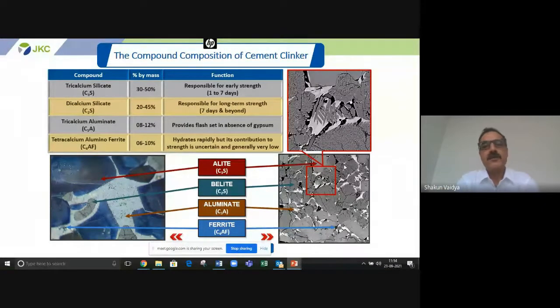These are the phases of clinker, and as is visible, C3S and C2S are the two major compounds which are responsible for the early strength. For 1 to 7 days, strength is solely due to C3S. So initially the gain of strength is very, very rapid in the initial 6-7 days. Then it tapers down, and almost 20 percent balance is through C2S, and small fractions to C3A for high early strength and C4AF as a flux.